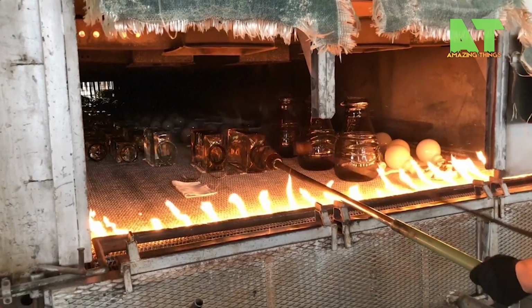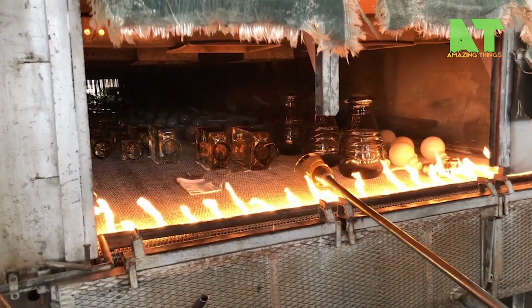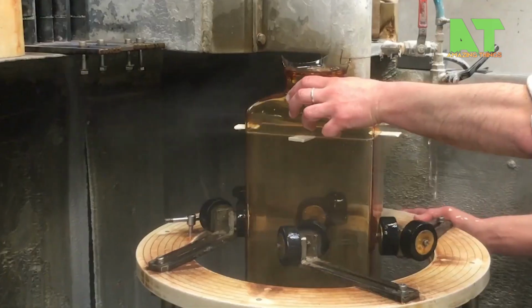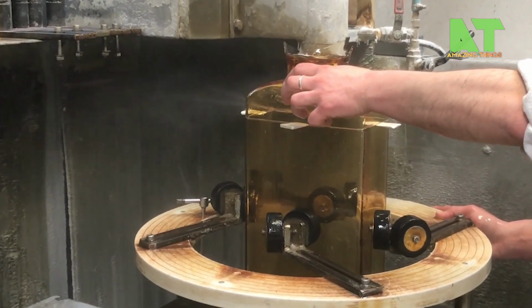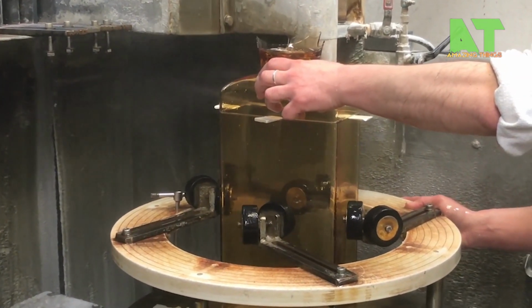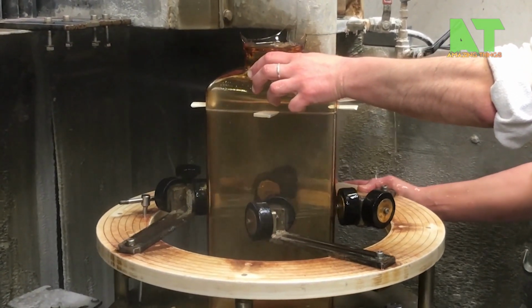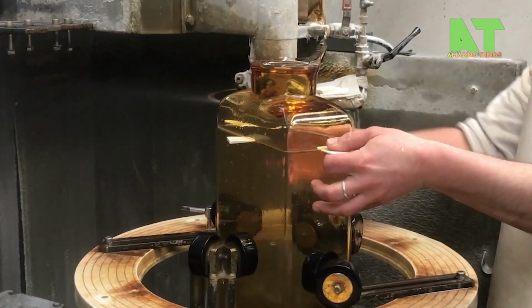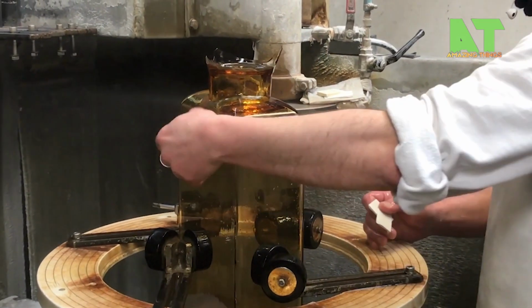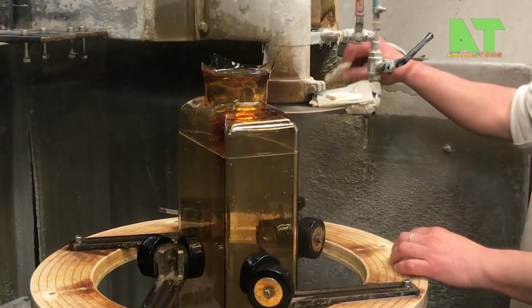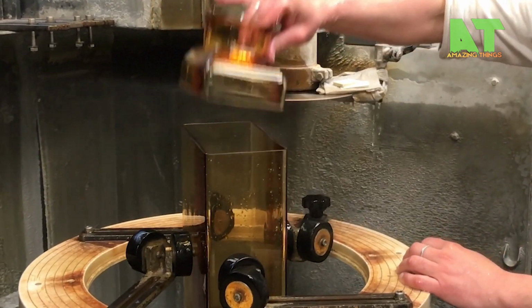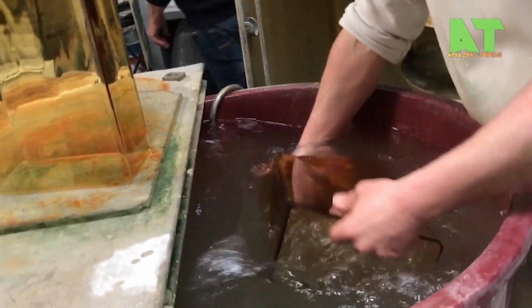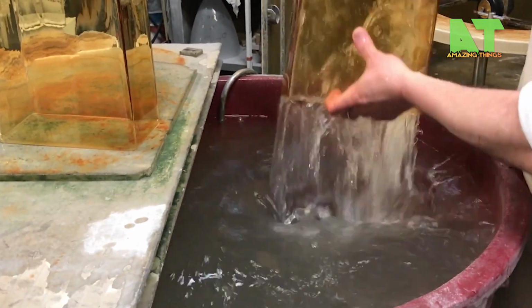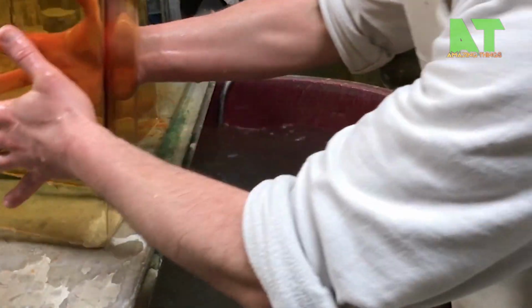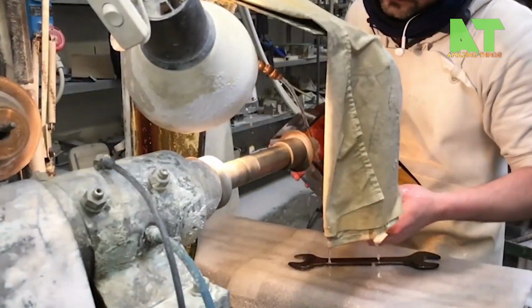What's remarkable is the timing. The craftsman has perhaps 60 to 90 seconds of working time before the glass becomes too stiff, requiring another trip to the glory hole. Every movement must be deliberate and practiced. This is where decades of experience show, knowing exactly when the glass has the right viscosity for shaping, sensing temperature by color and feel. The finishing process involves carefully transferring the piece from the blowpipe to a pontil rod, allowing work on what was previously attached to the pipe.